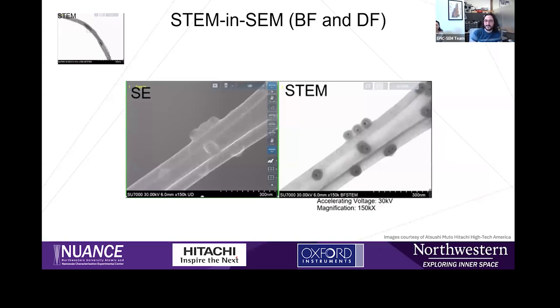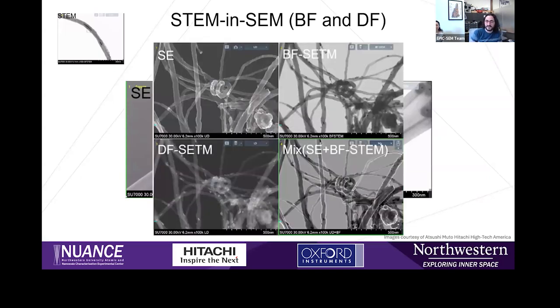This is, of course, bright field mode, so we can also look at dark field mode. Bright field mode detects unscattered transmitted electrons, so you end up with a brighter signal in the thinner areas or lower Z parts of the sample, like on these carbon nanotubes in the top right image. And dark field is just the inverted form of bright field. So the detector instead picks up scattered electrons and shows diffraction contrast, which highlights areas such as defects or different crystal orientations, which you can see in the lower left image.